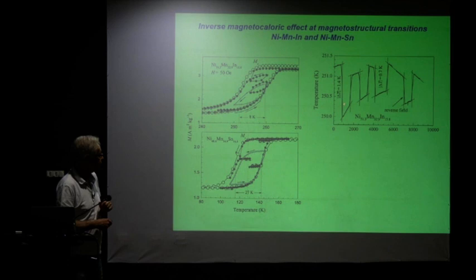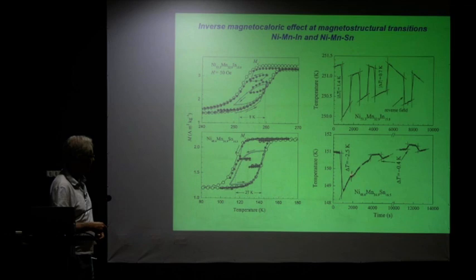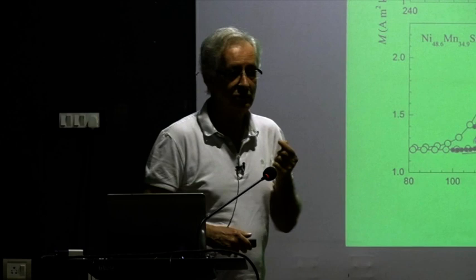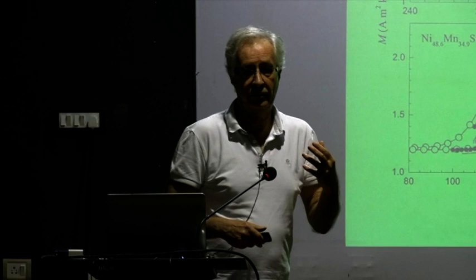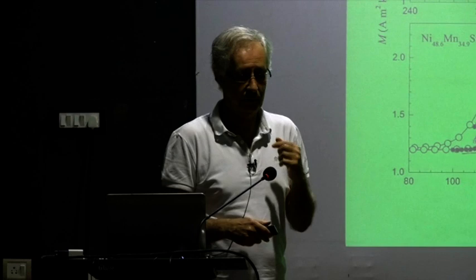We looked at this and said the initial shot here is 2.5 K — it was 1.4 K in the other case. Then we get so stuck in the hysteresis loops that nothing happens; there are no further subsequent shots. We said you either change the state of the system or you don't. If you're changing the state of the system, you have the magneto-caloric effect — you have the entropy change. This can be the inverse magneto-caloric effect or the conventional magneto-caloric effect.